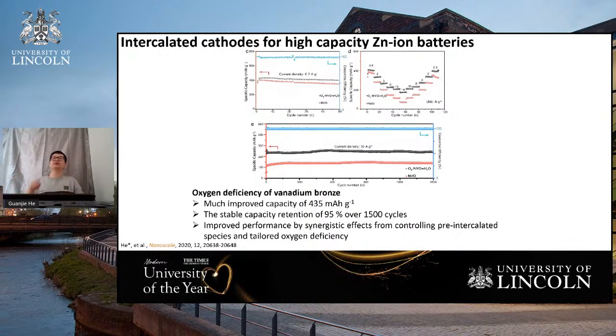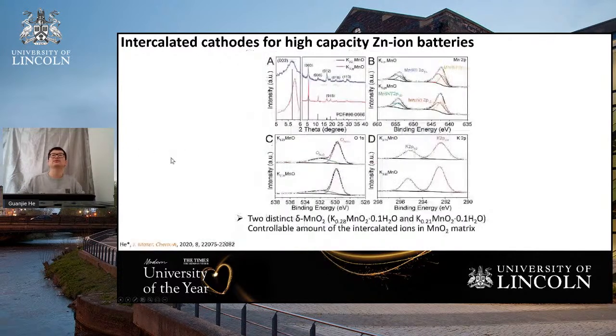And from this work, we develop a new material, and that shows the improved performance by synergistic effects from controlling pre-intercalated species and also the tailored oxygen deficiency. And following this work, we try to understand, will the amount of the pre-intercalated species influence the final structures or final performance? And we did the third work related to our cathode design.